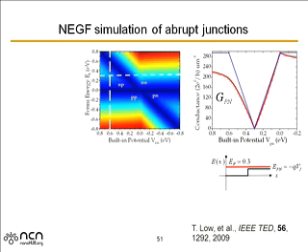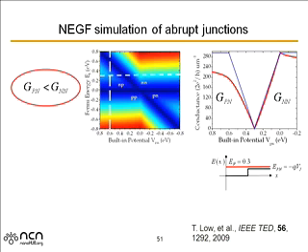However, if you make the potential barrier small, so you bring it down here, then the conductance goes up to a much higher value. And if you keep bringing it down, the conductance actually starts to drop. So what's happening there is you're having a bigger and bigger potential step, so you're getting reflection of the electron waves off that step. So you're getting quantum mechanical reflection that's lowering things. Okay, so the simulations also show us this asymmetry that you see experimentally.